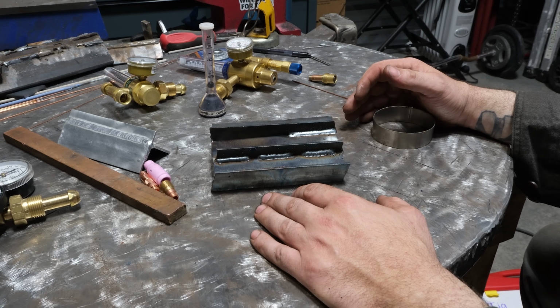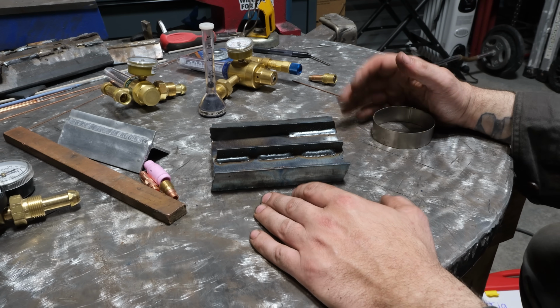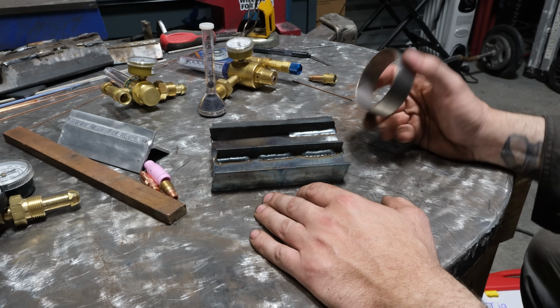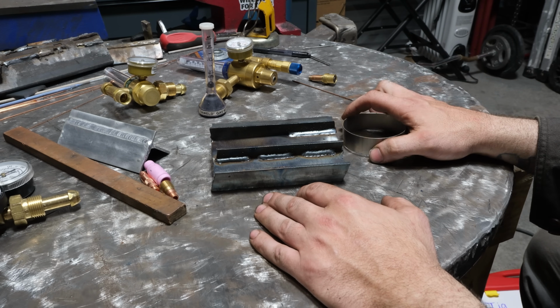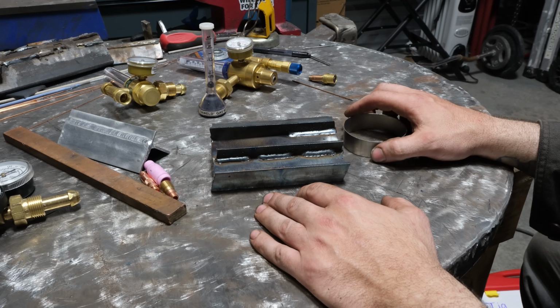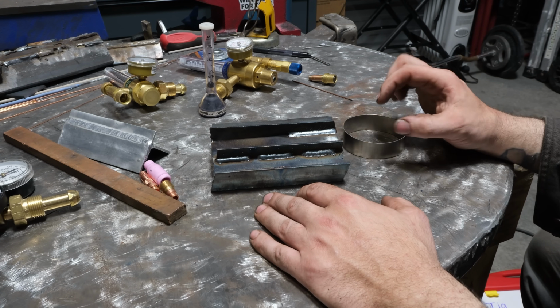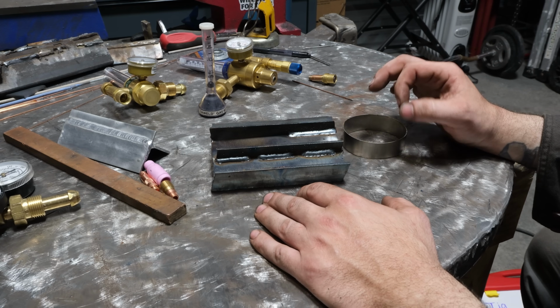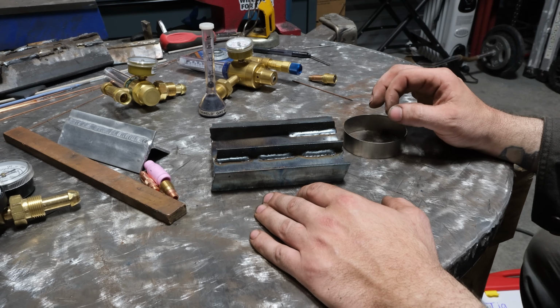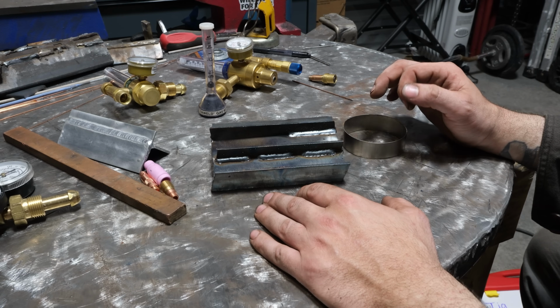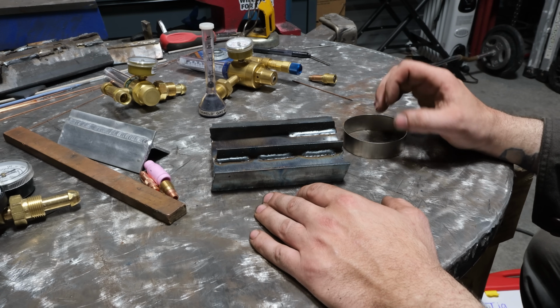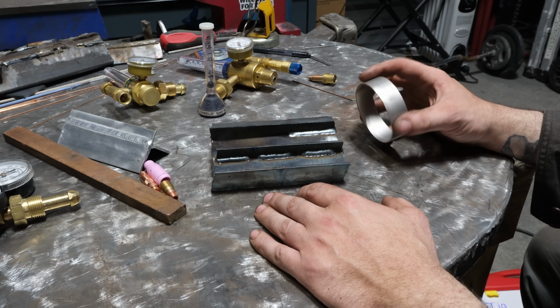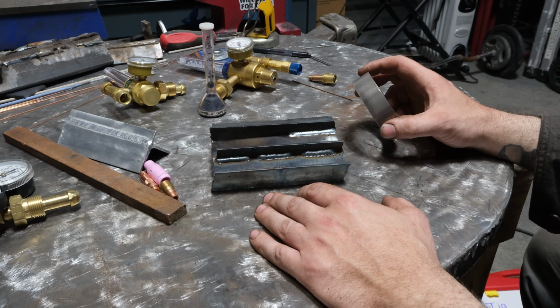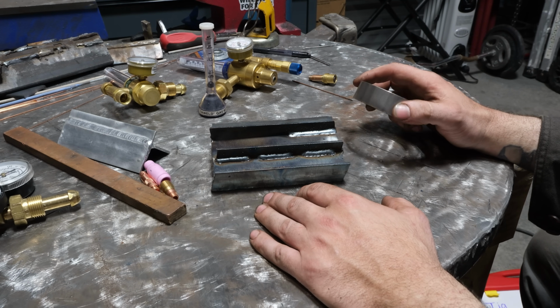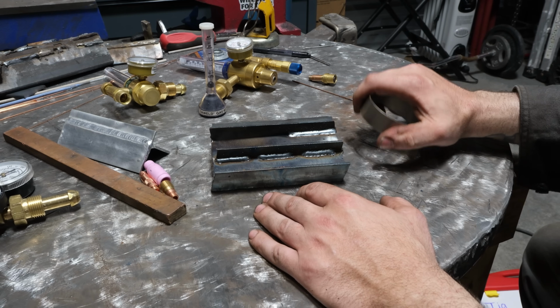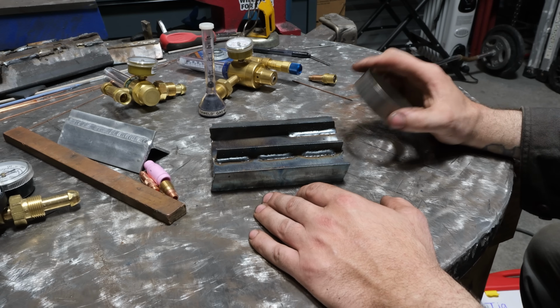Now, if you're going to weld on critical stuff, so in the case of TIG, titanium like this, or stainless, you have to use more gas shielding. Not only does it improve gas shielding, with a bigger cup and higher flow rates, it improves the weld pool. The weld pool's nice shiny silver, it reacts consistently, it doesn't react with oxygen. And in the case of titanium, any oxide color on titanium, the weld is junk, it's brittle. You squeeze it and it sounds like ice breaking, it's junk.